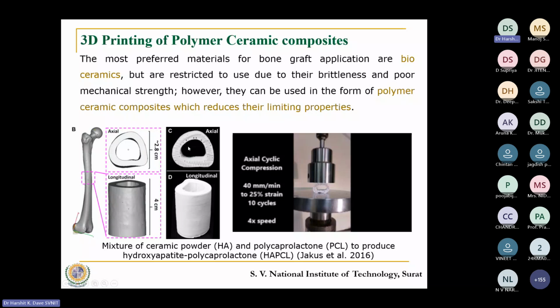The other thing is that these parts are created, a scaffold is created, and that scaffold is placed, and in between the bone also grows, and it helps to create a natural bone without losing the length of it. And when these parts were created from, say, ceramic powder, which is hydroxyapatite, mixed with polycaprolactone to create HAPCL, this is what is being found.